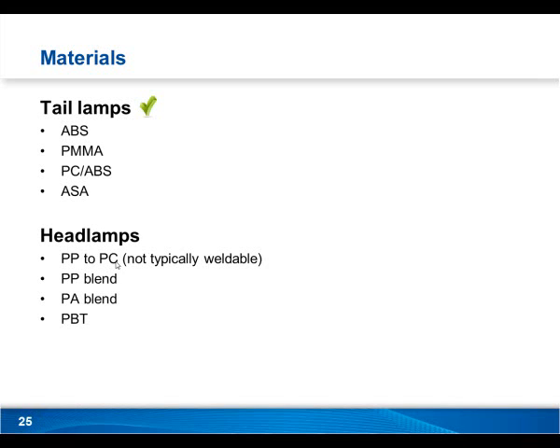The reason for this is because there are a few factors that go into the weldability of two different plastics. One is the melting range. PP to PC, they tend to have a similar melting range, but the other three factors they don't match up so well, which are the heat expansion coefficient between the two plastics is too high, and also the surface energy varies too much. These two plastics just don't like to be welded together. However, most headlamps are polycarbonate lenses to polypropylene housings, and so most of the time these are glued.